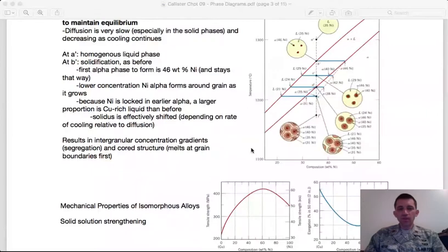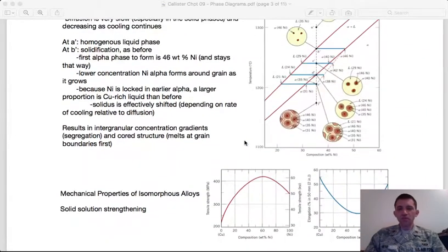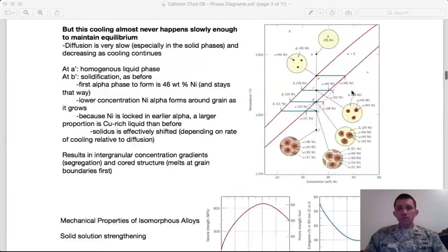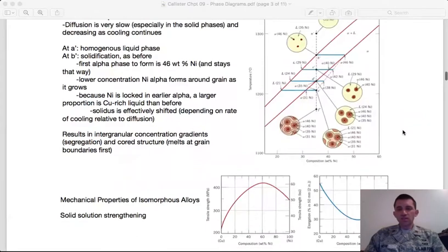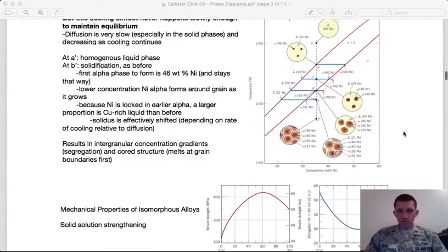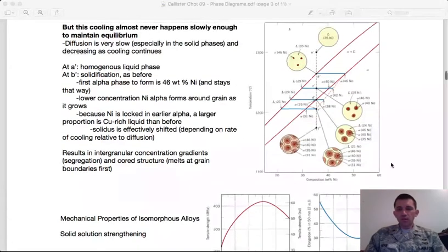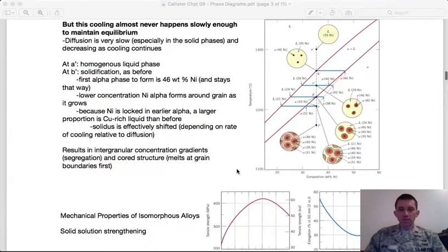And it gives you an intergranular concentration gradient, right? Meaning within one grain, you have a concentration gradient of nickel. And this is actually undesirable, because that means that at your grain boundaries, you have material that is going to melt initially at a lower temperature. And so that gives you less temperature resistance, and it means that at that lower temperature, your material is essentially going to fall apart at the intergranular level. And so it may be desirable to have a post-solidification heat treatment to allow that diffusion to occur and diffuse some of that nickel out of the core and into the rest of the grain.